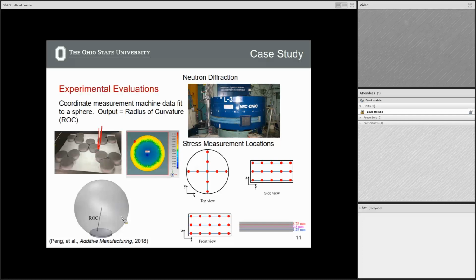And then from there you can fit all this data to what we call a radius of curvature, so this gives us a single number, a metric of distortion. So basically ROC goes up, distortion goes down. And then vice versa, right? So if we have a very small ROC, that means this fits a very small sphere, so therefore it has a lot of distortion in the part.